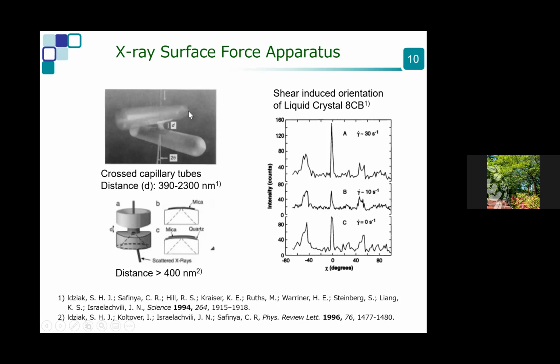They used crossed capillary tubes, or discs, identical to the SFA but with holes in the middle, and did X-ray diffraction studies of the shear-induced orientation of liquid crystal. But in their case, they could only study distances of about 400 nanometers and above. And if you remember my data, the confinement effect appears at distances smaller than 20 nanometers. So this is not sufficient for studying confined liquid.